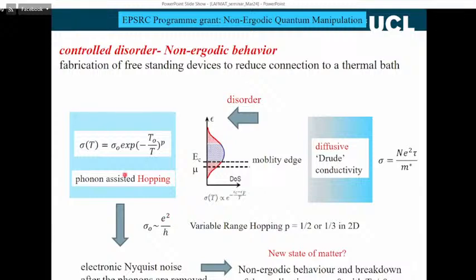So when we have this hopping, we have a slightly different temperature dependence. If P is a half, it's variable range hopping. We can also get a power law of 1/3 for different types of hopping. What's also interesting in this system is that the prefactor sigma naught is quantized, to the quantum of conductance, e²/h. For Mott variable range hopping, with P equal to 1/3, it's about 2e²/h. So even for different hopping mechanisms, we still have this quantized conductance.